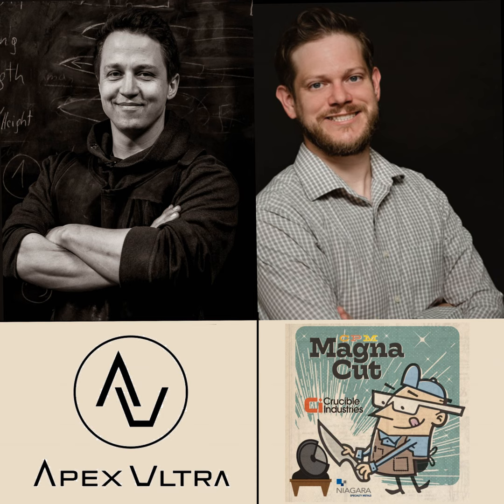So to go back to the questions and the proposed methods, I would put diesel and quenching oil and WD-40 all into the same category of, if your burner settings are right, you can use all of them. They will all burn because oil does not exist at 1150 degrees. It just burns away. So by the time your entire billet is heated up to the full temperature, there's not much left of the oil anyways. So just make sure that you have a somewhat pure oil that doesn't include any additives that would still exist at that temperature.